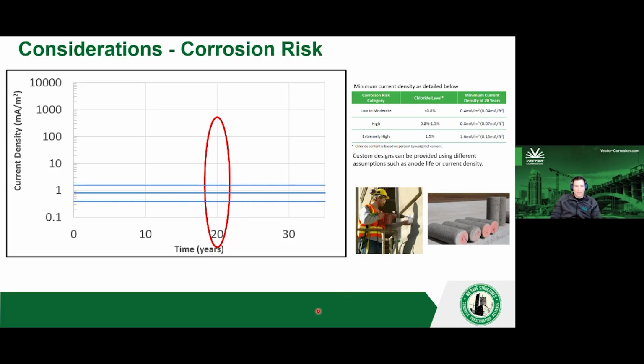And there are actually three levels that we at Vector have found are sufficient through our 20-plus years of research and field trials. The minimum amount you're going to want if you're in a low to moderate risk, which is less than 0.8% chloride by weight of cement, is 0.4 milliamps per square meter. Then you have a high range, 0.8 to 1.5%, 0.6 milliamps per square meter. And then you have an extremely high range, anything above 1.5%, 1.6 milliamps per square meter. And where can you find these numbers?